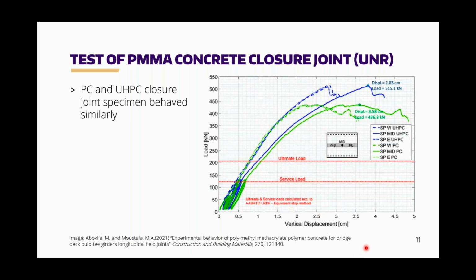And so you can see the test method here. They took this assembly up to a service level several times, cycled it there, and then pushed it until they reached the peak strength. And the red lines there show you the AASHTO LRFD service and ultimate load levels. So both specimens achieved greater than the ultimate load level based on AASHTO LRFD.